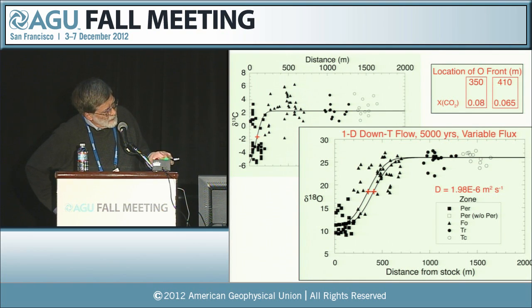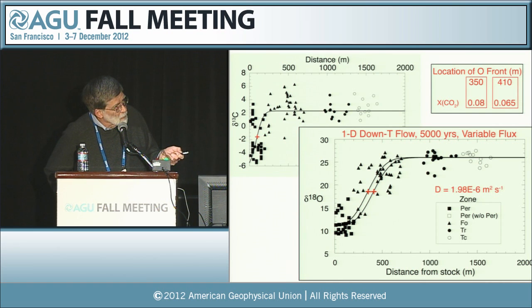Now, in order for the two different fluxes that match these two different center points for the oxygen profile to duplicate the carbon center point at about 100 meters from the contact, that requires different mole fractions of CO2 in the fluid. If the center point of the oxygen front is at 350 meters, the infiltrating fluid needs an XCO2 value of about 0.08. If it's at 410 meters, if they're further separated, the mole fraction of CO2 in the fluid can be smaller, at about 0.06.